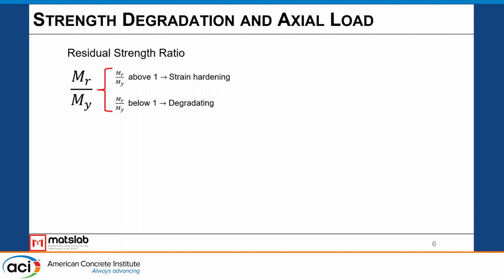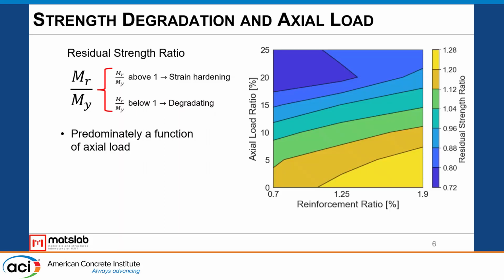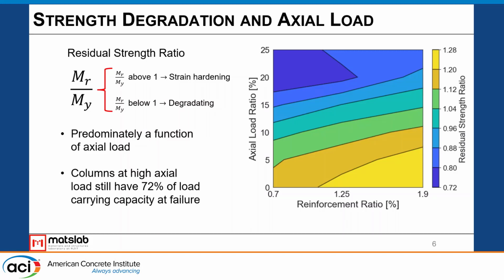And we also wanted to understand how this residual strength ratio is a function of reinforcement ratio as well as axial load. So we plotted that as a contour plot. What we can first see is that these contour lines are reasonably horizontal, so it's predominantly a function of axial load. And more importantly, what we can see is this dark blue at the top: column subjected to 25% axial load ratio. We still have 72% of load carrying capacity at failure. So these columns are not just abruptly failing once they reach their nominal capacity. We still have substantial load carrying capacity even at that ultimate failure state.